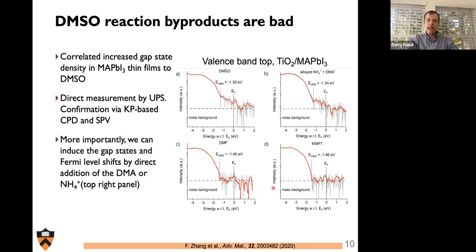And in the case of using a solvent additive like NMP, which doesn't have any of these byproduct reactions, we can see a very similar valence band maximum, that there's no introduction of any defect or gap states into this system. However, if we use DMSO, we can see that this gap, this forbidden gap, now has some states in it. And these have been introduced through the act of introducing dimethylammonium and ammonium to the film. That can be confirmed in the upper right panel here, B, where we've specifically introduced ammonium and dimethylammonium, but without any DMSO present in the ink. And we can see a similar manifestation of these gap states.